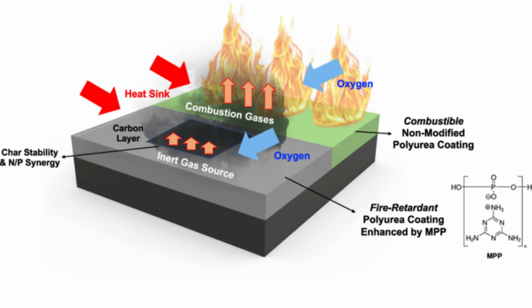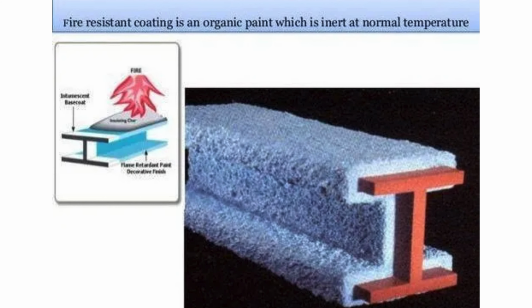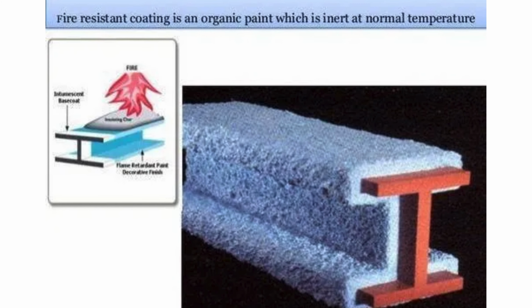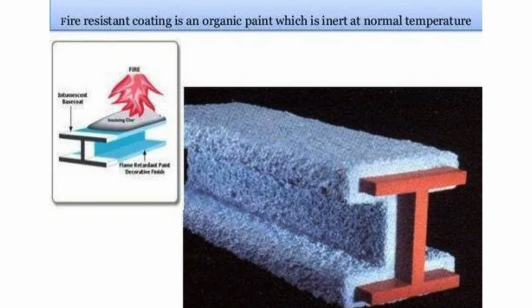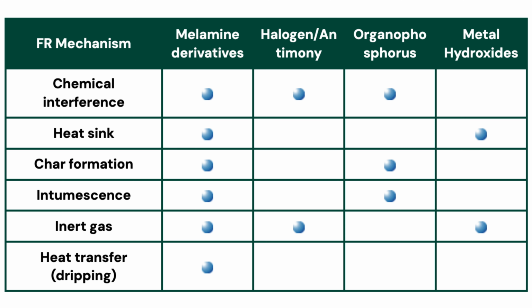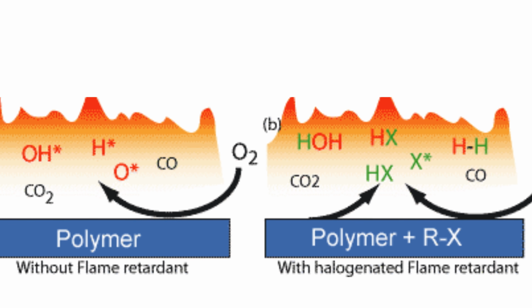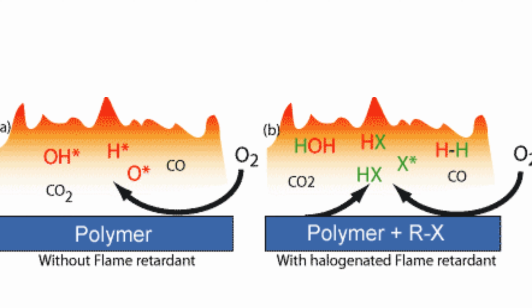The result is a multicellular, expanded carbonaceous foam that blocks heat and oxygen, reducing substrate temperature rise and delaying ignition and structural collapse. Categories of fire-retardant coatings. Non-intumescent fire-retardant coatings rely on inorganic fillers, ATH, MDH, zinc borate, TiO2, nanoclays. Mechanism, cooling, oxygen dilution, barrier formation. Used in plastics, adhesives, cables, and electronics.